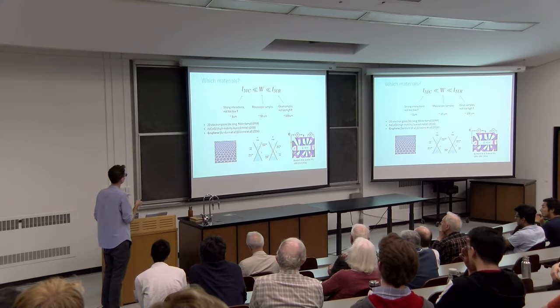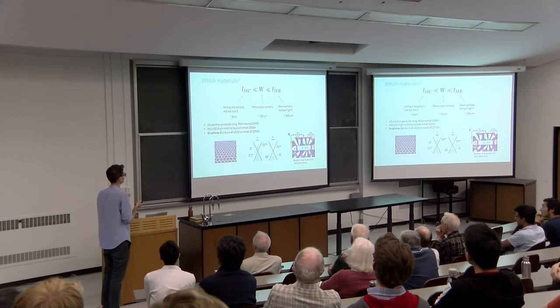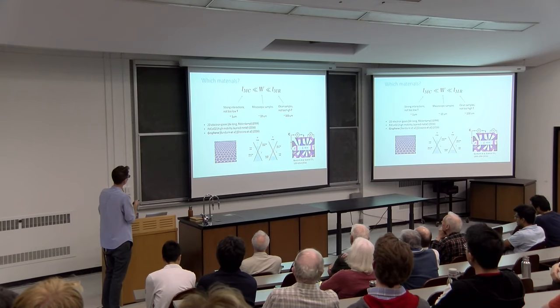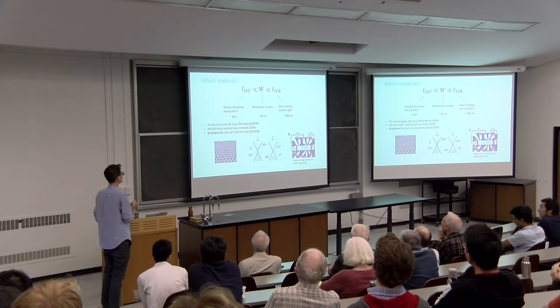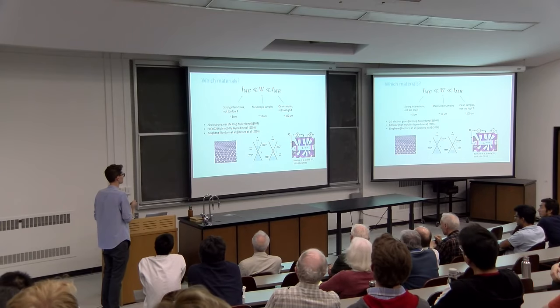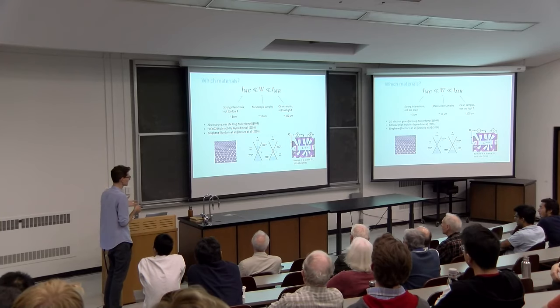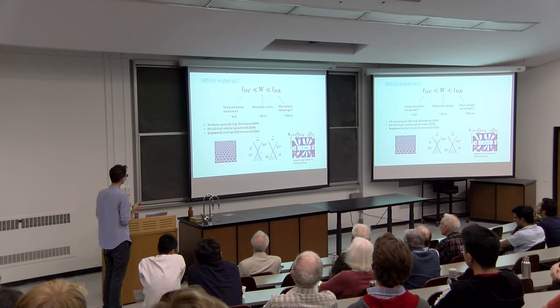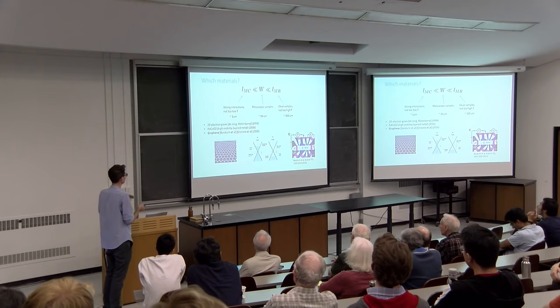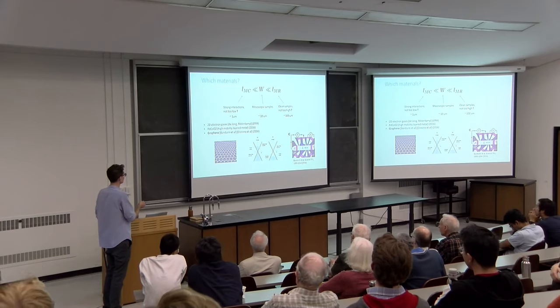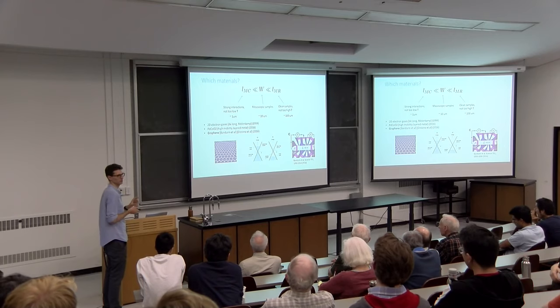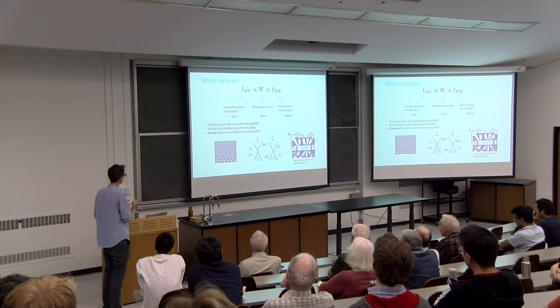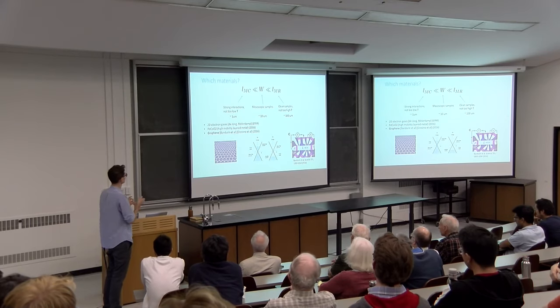You want to be able to make mesoscopic samples of intermediate sizes. There were initial experiments in the nineties, and more recently experiments in high-mobility metals like palladium cobaltate and mostly in graphene, with a lot of experiments since 2016. Graphene has several advantages: one can make very pure samples, and by gating the graphene sheet one can change the Fermi energy, giving an extra knob to tune L_MC. If you make the Fermi energy smaller while keeping the same temperature, you increase the interactions and decrease L_MC. So temperature and gate voltage can both be tuned to achieve the hydrodynamic regime.